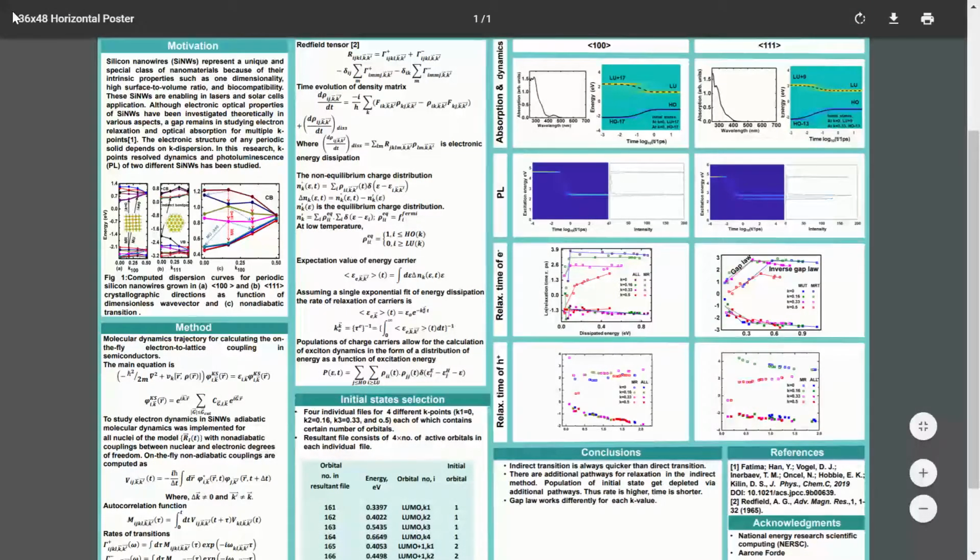So I would even say that this is not PL because it's not realistic, because you only get emission, either of these, typically from your lowest states. Your high states that are there for a very short time, you don't see PL from. So the states at like 4.5 and almost 5 aren't there experimentally. It is true that they are not real photoluminescence. So I'll change the name. If I cannot calculate real ones, then this name must be changed. Okay.